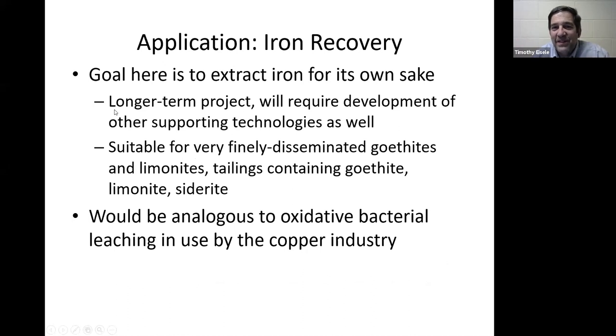So the first application that occurred to me, obviously, was to use it to extract iron. And ideally, this would be suitable for ores that are hard to process with conventional methods. The conventional iron mining operations are mostly going after magnetite and hematite that can be ground and break pure mineral grains apart from one another. And then you can physically sort them using magnets or froth flotation or other separation processes. But there are a lot of ores where this isn't actually practical because the grain size is so tiny. And so we need something that's going to chemically attack the metal to dissolve it.